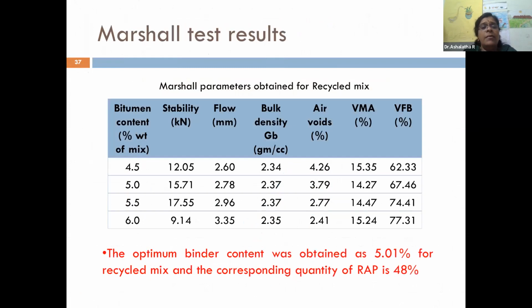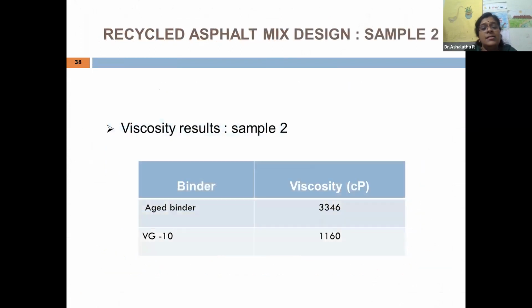Then Marshall parameters were determined for the recycled mix for different bitumen contents, and the optimum bitumen content was obtained as 5% for the recycled mix, and the corresponding quantity of RAP was 48%. You can see throughout our presentation that we are getting the RAP content on the higher side, especially when you use Sasobit. Then the same process was repeated on the other sample.